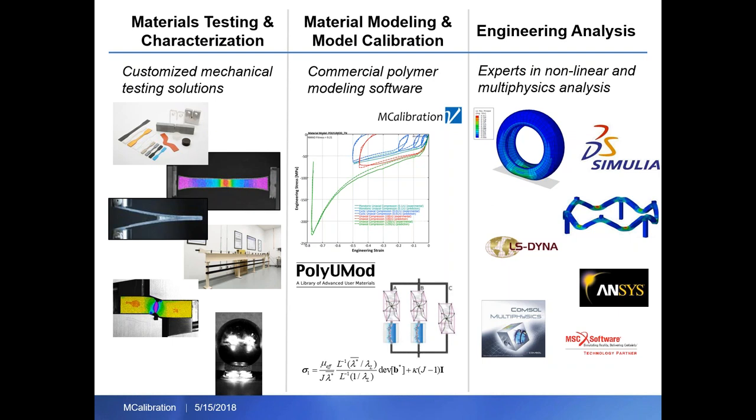I see there's one here - before starting the inverse calibration, do you first try to get the best guess from classical MCalibration one element with stress-strain data approximated? Yes, I do. I'd say it's pretty rare if never that all we have are inverse calibration data. For example, with the tension dog bone example with the necking, we take the engineering stress and engineering strain that we calculated from the experiment and we do MCalibration using those single element finite element models and get very close. Then we might either get rid of those load cases and use only the inverse, or we'd supplement the single element MCalibration classic load cases with the inverse to capture the necking. We'll have similar things in the other cases. Good question.